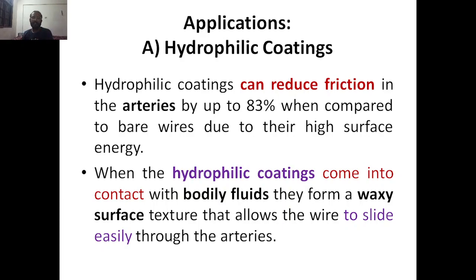Hydrophilic coatings can reduce friction in the arteries by up to 83% when compared to bare wires due to their high surface energy. Hydrophilicity is very important for guide wires because the wire is surrounded by blood. When the hydrophilic coatings come into contact with bodily fluids, they form a waxy surface texture that allows a wire to slide easily through the arteries.